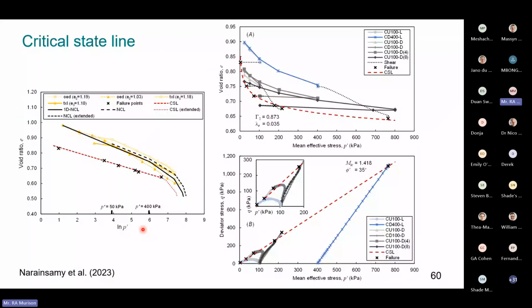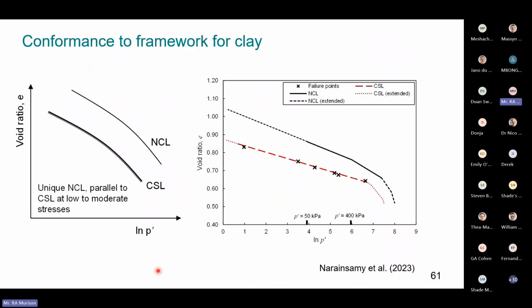I've completely run out of time to be able to discuss the triaxial testing in any detail, but as part of the study, some triaxial consolidation tests were done in order to establish the isotropic normal consolidation line, which, if we assumed a constant K0 value for our odometer tests, was approximately parallel to the isotropic line, which complies well with the theory as well. And then drained and undrained shearing tests in triaxial compression were used to establish the critical state line. And there's, in addition to these, like I said, 30-odd triaxial tests in Yashay's PhD. So definitely keep an eye out for that. Some very interesting stuff. But if we were to summarize all of this, our normal consolidation line and critical state line that we determined were approximately parallel as well.